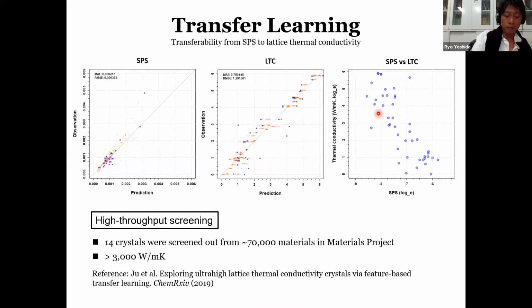This shows the predicted values of the pre-trained model on the SPS, with prediction and observation on the horizontal and vertical axes. This was transferred to the model on thermal conductivity. This shows the result of the tenfold cross-validation performed within the 45 data points. As you can see from this figure, they exhibit good agreement.